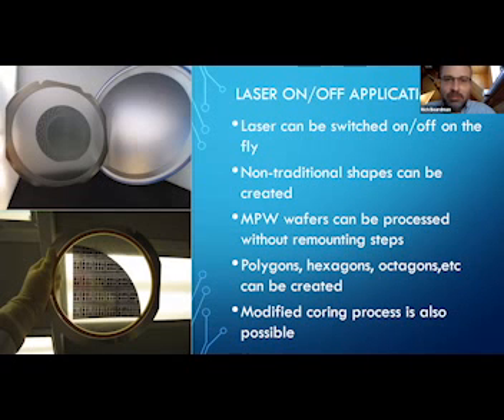So some of the nuances to the stealth process now, as I mentioned previously, we're able to switch the beam on and off. So you can see it cut octagonal shapes, or, this was more experimental right here, we did a modified coring of a wafer. So we cut in multiple channels to take an 8-inch wafer and core it down to a 6-inch wafer. That's not really what stealth is intended for, but was just kind of a neat little science experiment.